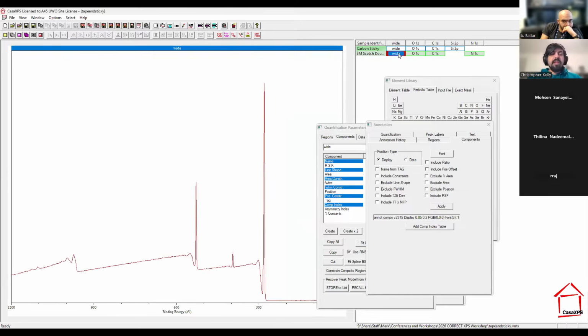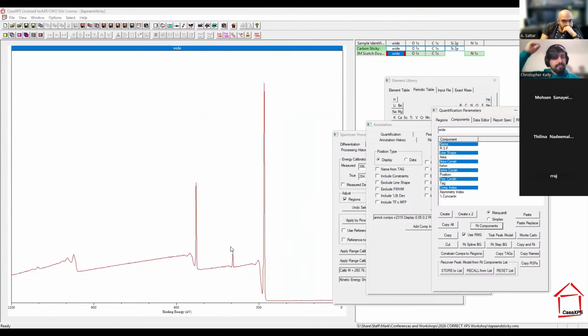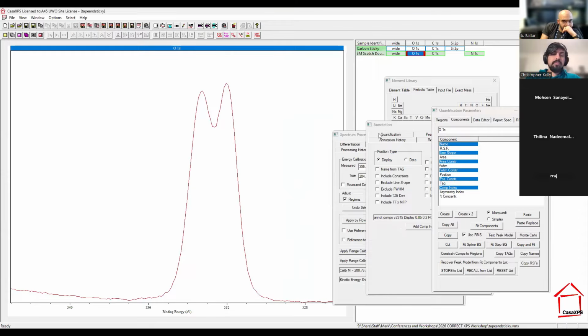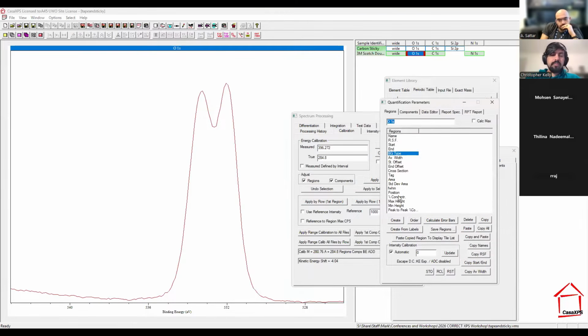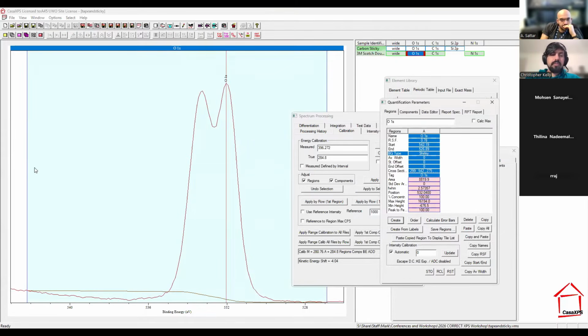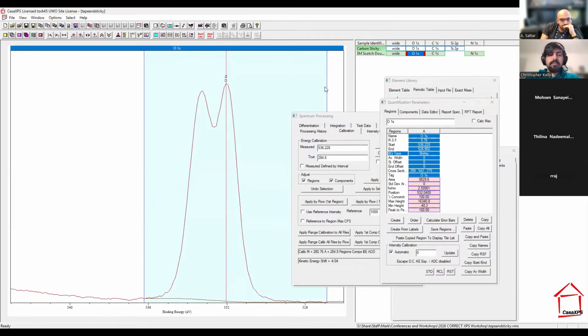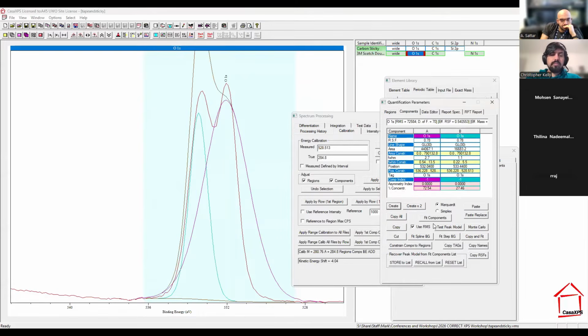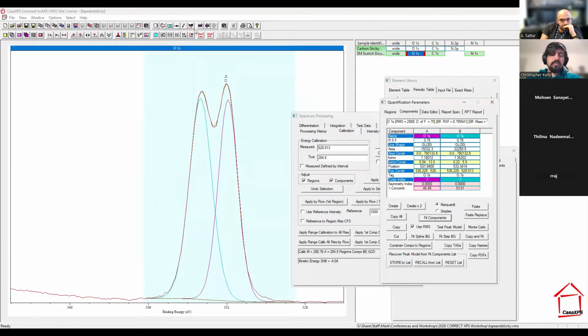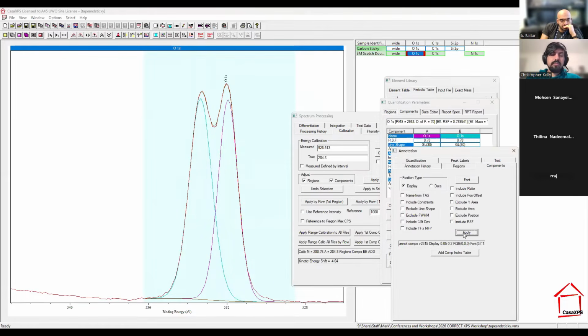Maybe we'll take a quick peek at the survey spectrum. In the survey spectrum, we see we just have carbon, nitrogen, and oxygen. So there's no other contributions other than organic type oxygens present. And again, we can go in and put a region down across the background, create a couple of peaks, see how they fit. It's not too bad. We've got some pretty good resolution.